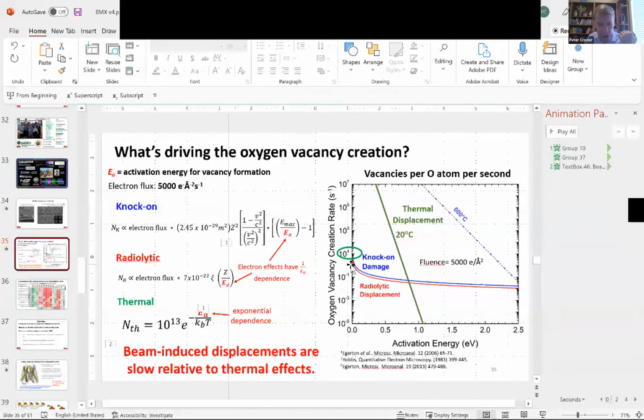And we're plotting that on this graph over here, but we're keeping the electron dose fixed, and we're plotting the number of vacancies created by knock-on or radiolysis as a function of the vacancy creation energy. In other words, we're letting EA be a variable, and these are the two graphs that you see here. And so you can see that there's not a strong dependence: the number of oxygen vacancies created only varies by a factor of 10, depending on what the oxygen vacancy formation energy is.